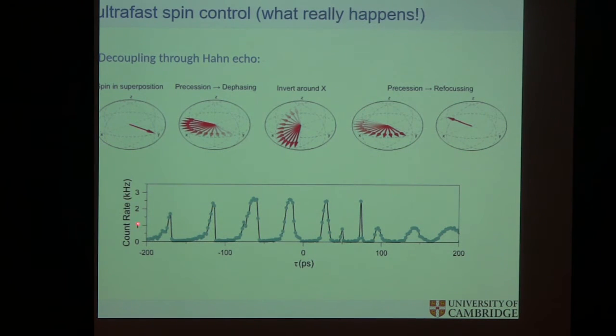And the reason for spin echo looking like this is because we don't have a single spin with some boring dephasing taking place. We have a nice clean spin coupled to a spin reservoir of about 10,000 to 50,000 nuclear spins, and you're polarizing them. They're in direct contact interaction, and over a long time scale, but short compared to the length of your experiment to sweep, you're continuously polarizing the nuclear spins.